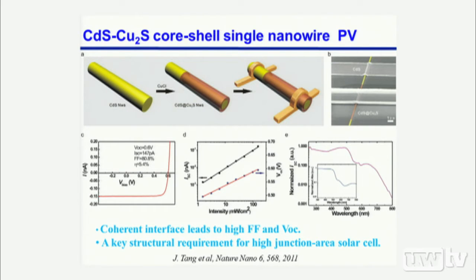We demonstrate that it's possible, for a high junction area solar cell, to still have a very high fill factor and VOC. At this moment, this first generation solar cell has an energy conversion efficiency of roughly 6%. This efficiency is largely limited by the amount of visible light absorber we have. Here, the visible light absorber is copper sulfide. For this 6% solar cell, we only have 10 nanometers of thickness in the copper sulfide coating.